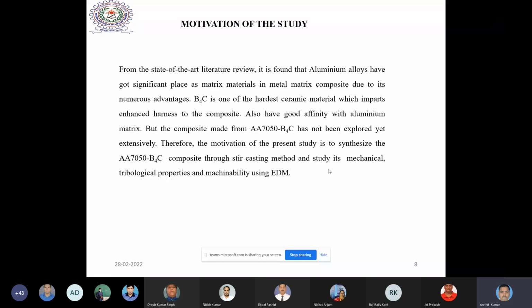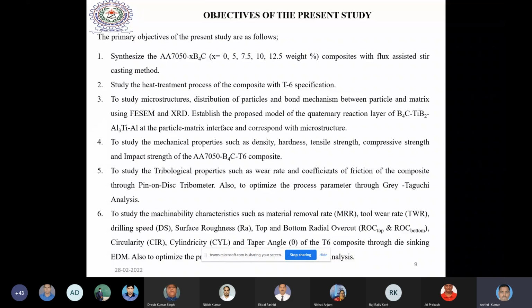Aluminium alloy B4C based composite material, and this material has good affinity, since B4C has good affinity towards the aluminium. So I have chosen this reinforcement ceramic particle B4C, and the size, if I remember, was 100 micron B4C particles, which I have used here. So the objective was also clear, to develop a composite. I have gone up to 12.5% of B4C.